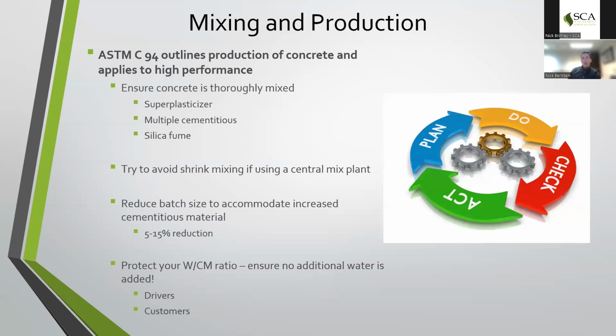We try to avoid shrink mixing in any of these events. Occasionally, we do mix uniformity testing just to ensure, knowing we have some high volume pours coming up, that if we need to shrink mix in order to achieve the high volumes requested, we can do that, but verify that before any sort of changes are made. If you need 90 seconds, 2 minutes, 3 minutes, doing a few test batches can really help work the kinks out of that to make sure that you're going to deliver a consistent product.